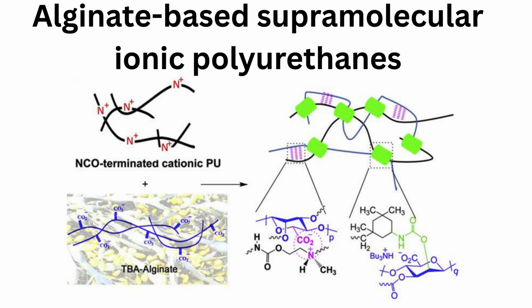The high response speed and high viscosity of polymer materials containing ionic bonds have led to their significant attention in the field of self-healing materials. Scientists successfully synthesized and characterized an alginate-based polyurethane elastomer exhibiting supramolecular interactions in the solid state. The material was constructed using ionic supramolecular motifs.